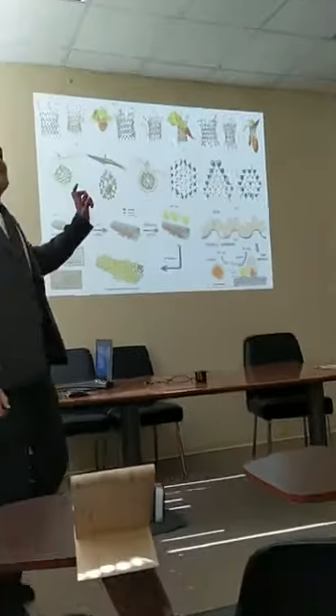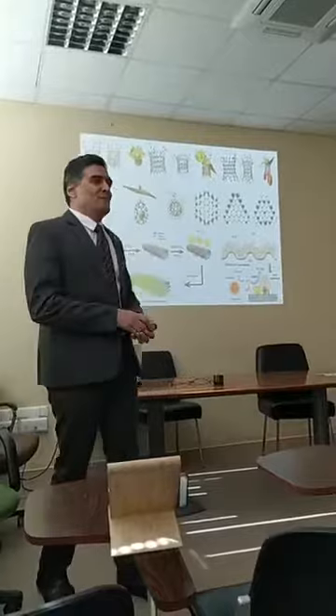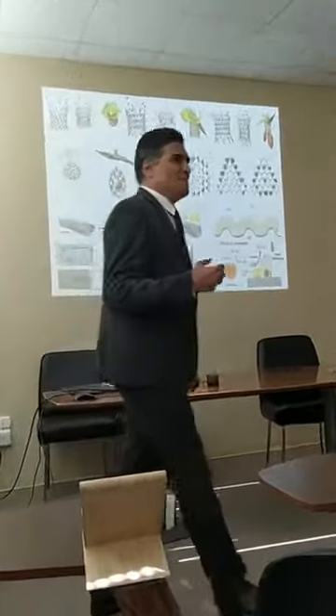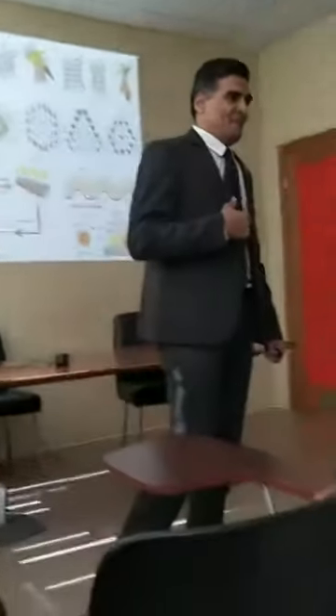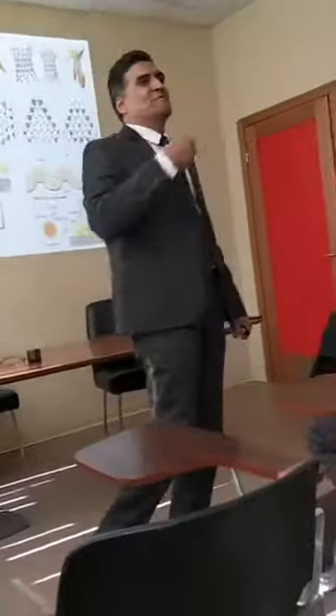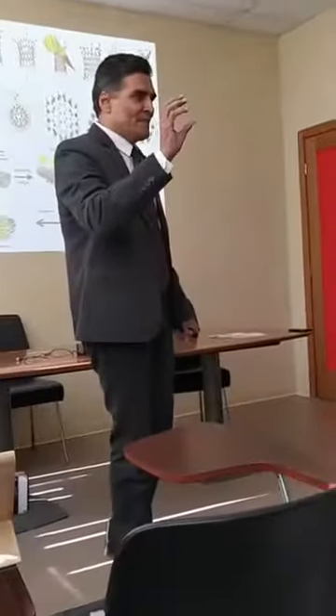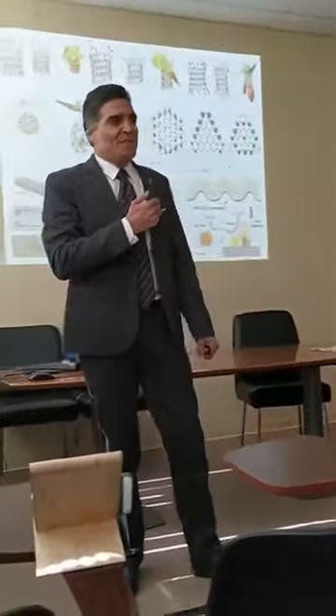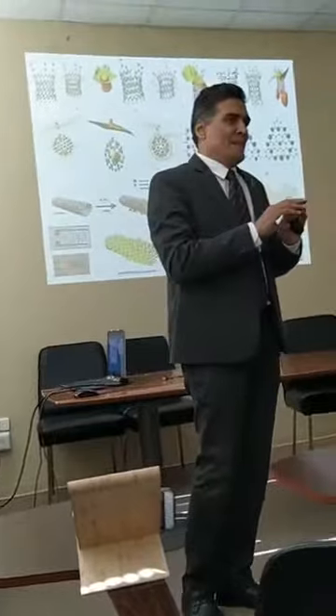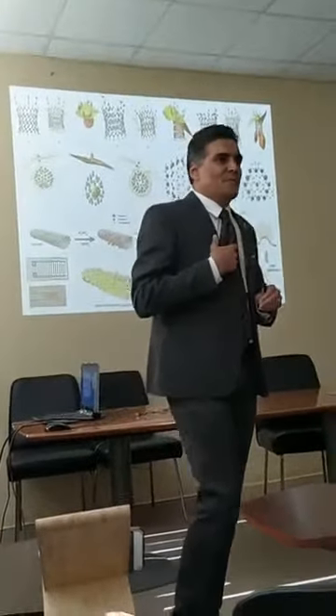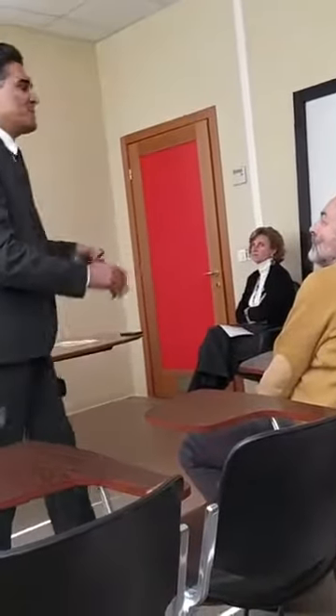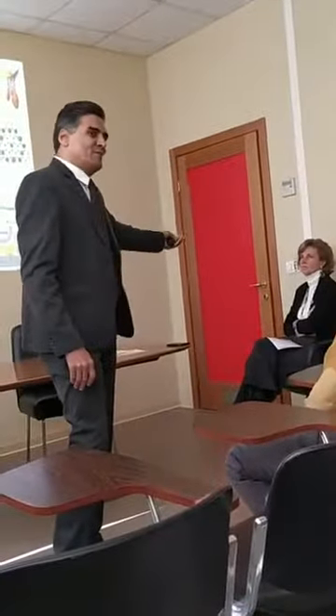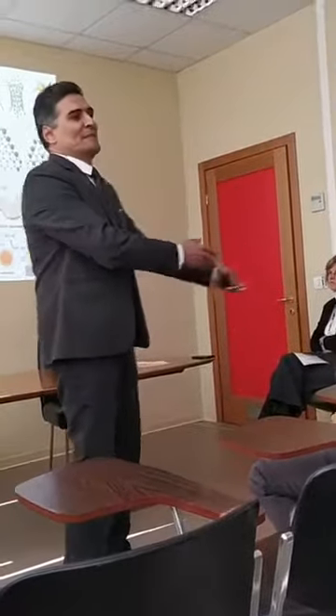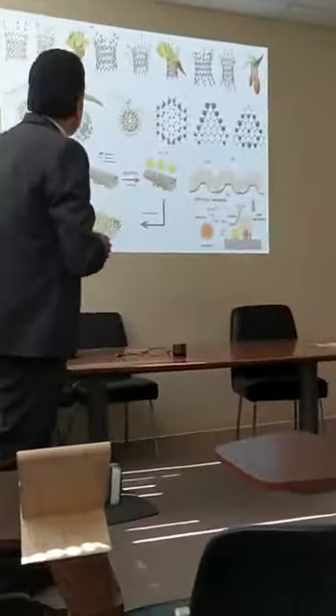And then what we are doing is to calculate, if we are going to describe the interaction between some gases and the metal oxide, for example, we have to study something called selectivity. If I have many gases, I have to be selective for a certain gas. So selectivity could be determined by this theoretical method through the energy of interaction. If I interact with structure A, it costs 3 electron volts. If I interact with structure B, it's 4 electron volts, so this is the more probable one. That's why we have different schemes like this.